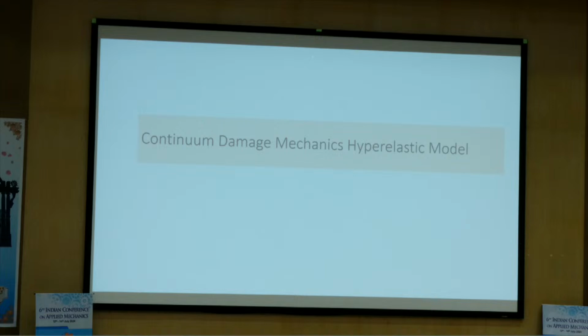Why do we need a hyperelasticity model? Because the fiber could be polymer fiber. When a projectile hits the target, the back surface of the target is going to bulge. When it bulges, the fiber is stretching. It could stretch up to 100%. So I have seen some experiments with high-speed camera. The back ply, they just bulge. And so then how can you use just a simple elasticity model for the fiber? For carbon, I can understand it, brittle carbon, it breaks. But then for polymer fiber like polyethylene, polycarbonate, S2 glass fiber.